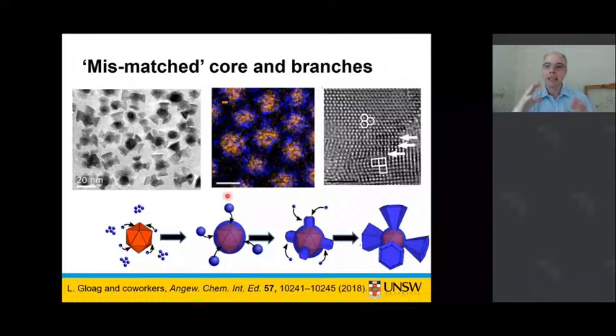So again, for those of us who really enjoy these mechanisms, we looked at two different seeds to see two different types of particles, two different approaches. So if we use gold metal seeds, essentially you don't have a good lattice matching between gold and ruthenium. There's a big lattice mismatch. So it means that the ruthenium atoms can't epitaxially grow and stack onto your gold core.